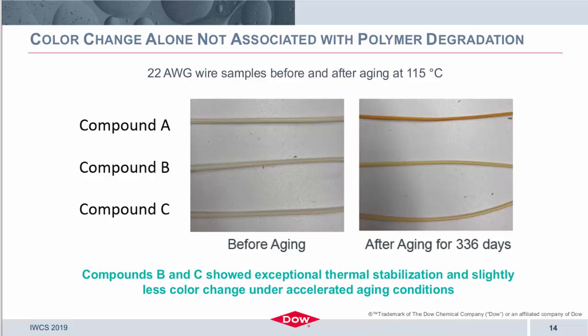One important point to note is that there is a color change that occurs when polymers age. However, that's not always associated with polymer degradation. So in the case here, we see compounds A, B, and C on the 22 gauge wire samples before and after aging. While compound A does show slightly more color, a darker color than the other two, there are other things that come into play when color is considered, such as the antioxidants and the stabilization package used. So color alone is not associated with polymer degradation. It may correlate depending on the additive package and the different studies that are conducted, but color alone is not going to be a good predictor of aging conditions and aging performance.